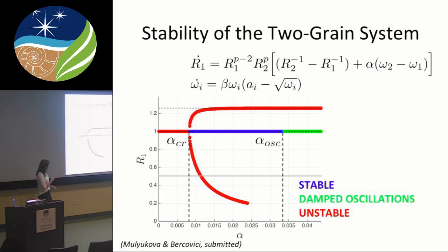When alpha reaches a critical value, alpha critical here, you now have an emergence of a stable branch, this is in blue, of stable solutions. This means that at this point, there exists a solution where dislocation density is capable of offsetting some of the forces associated with the grain boundary curvature. It doesn't mean the system will necessarily go to that state, because you can still be outside of that valley of stable solutions, but it just means that the steady state exists.